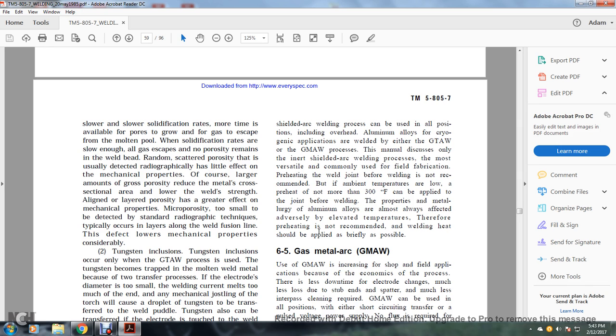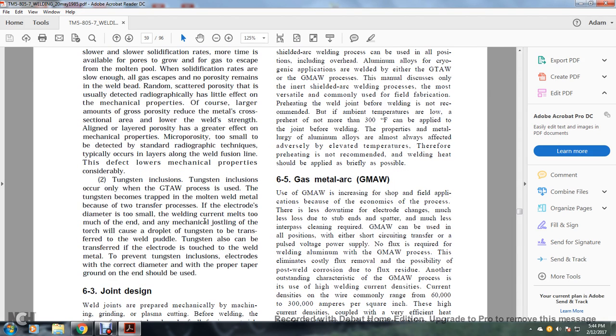Of course, the larger the amount of porosity, the more it reduces the metal cross-sectional area, lowering strength, while aligned or layered porosity has a greater effect on the mechanical properties. Microporosity is too small to be detected by standard radiographic techniques and typically occurs in layers along the weld fusion line. These defects lower mechanical properties considerably.